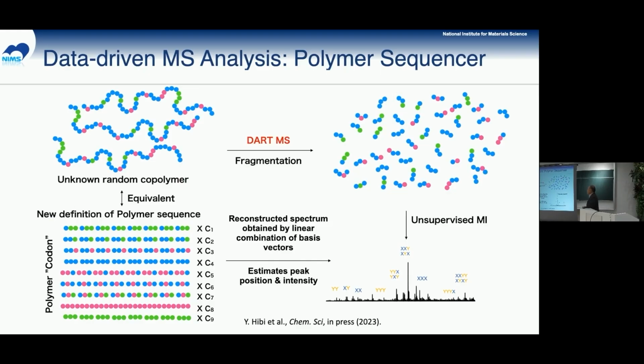So by using mass spectroscopy, we first fragment the polymers to get a big data pool of the fragmented polymers. Then we use unsupervised machine learning techniques, the NMF method, which I'll tell you about on the next slide, to classify the data. It's unsupervised, and here's the very important part. First, this is an unknown random copolymer. We don't know the sequence. It is fragmented by heating, chopping the main chain of the polymers, making a pool of fragments. Then by using machine learning, you can tell which spectra correspond to these short species, for example blue, green, blue, green, whatever.